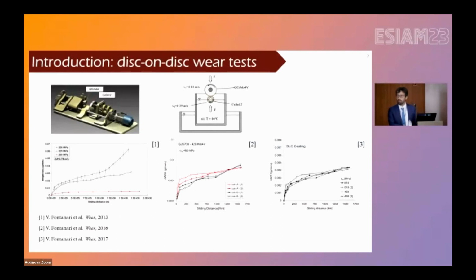Okay, so we have been investigating several ways of getting rid of copper. The quest is not so recent. Here we see previous attempts we carried out in the last 10 years in cooperation with an Italian company, C-Corp, producing gear motors for elevators. We used a test bench in disc-on-disc rolling-sliding conditions, in lubricated conditions. So we compared the conventional tribological pair constituted by quenched and tempered steel against bronze. And then we tried to compare the wear rates of other tribological pairs. So we replaced the bronze with cast iron, and we replaced bronze with a DLC coating on a steel substrate.